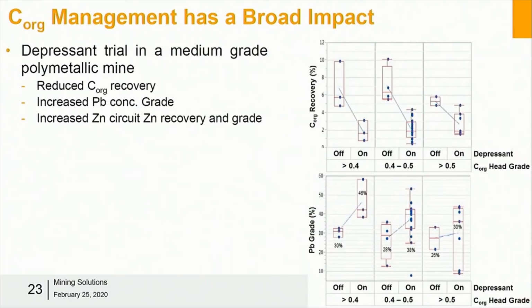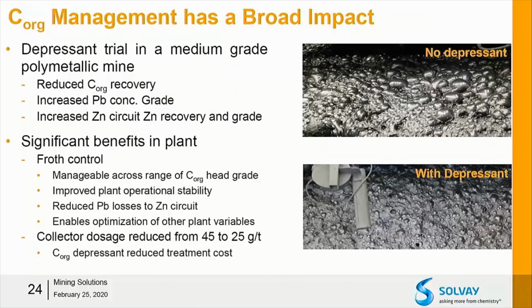Okay, I'd also like to talk about depressants. So this is data from a depressant trial that our commercial team ran on a medium grade polymetallic ore. And so what you see in the metallurgy is actually what you would expect for an effective depressant. Carbon recovery goes down and lead concentrate grade goes up. And so that's what you see, and there's definitely a lot of benefits there. We saw some improvements in zinc circuit performance as well. But the true benefits in the plant really came from froth control.